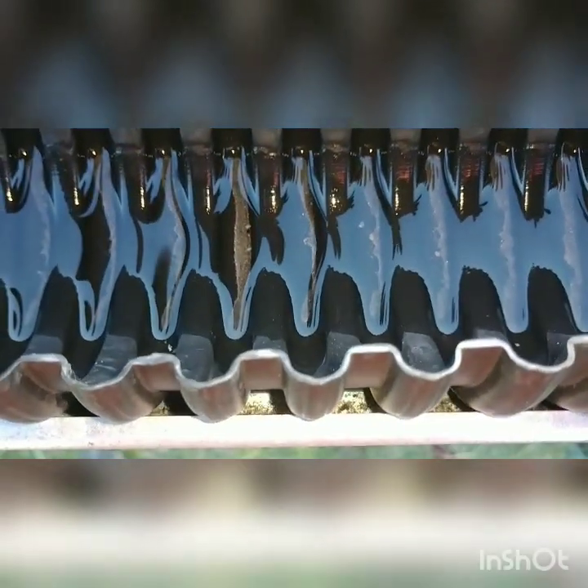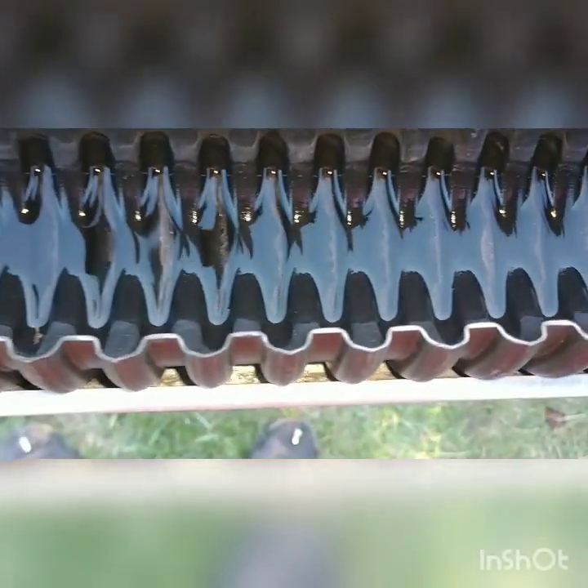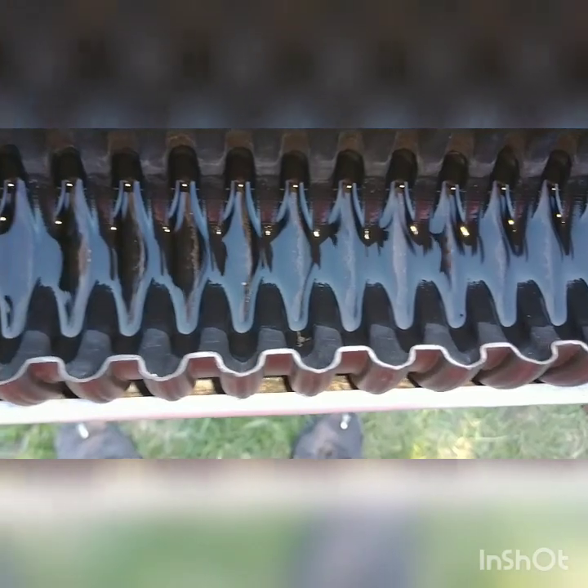Yield expectancy on chips like this from my experience is about half a gram to 0.75 per pound. So if I got a gram and a half out of this I would be pretty alright with that. As you go down the sluice there's some stuff that looks like gold but is in fact copper pieces and copper dust. Going back up to the top — this is in fact gold; you can see the bond wires and the yellowness.